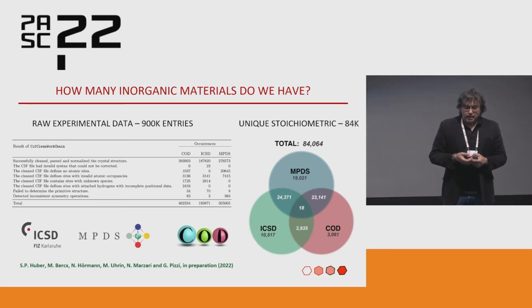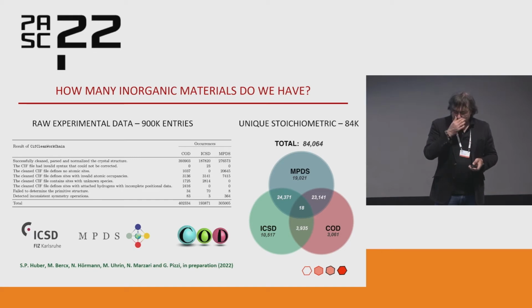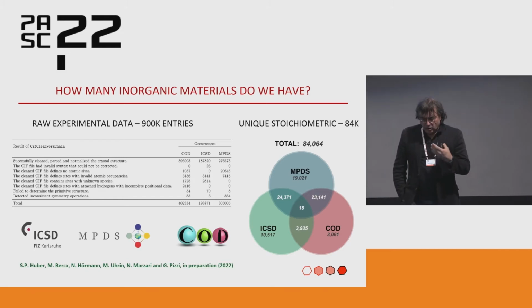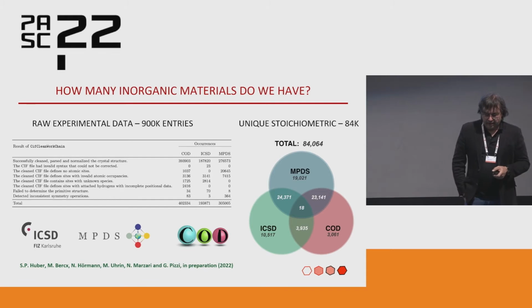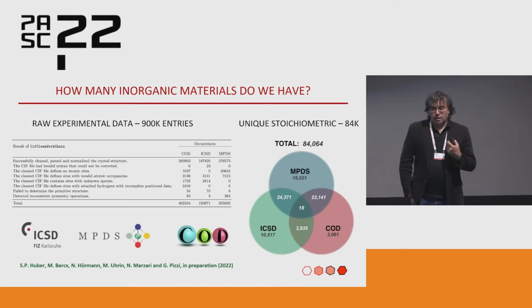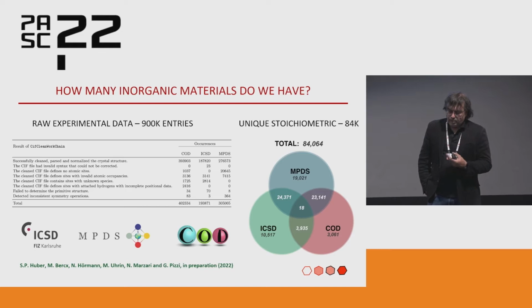Well, luckily, we have databases that have been collected over the years. I should point out a very relevant Swiss effort that has been going on through the Pauling File for 30 years, with 20 crystallographers in Lviv, in Ukraine, basically reading the literature, curating it, and passing it into their databases. These days, we have a number of databases. These are three of the major ones, with roughly a million entries, but if we look at stoichiometric compounds, with integer compositions, no alloys, no missing atoms, we have 84,000 different inorganic compounds.